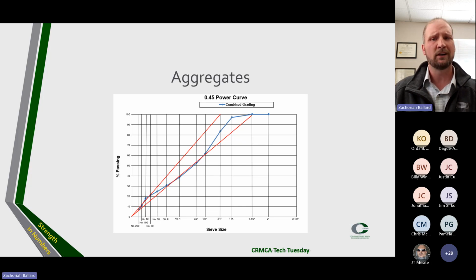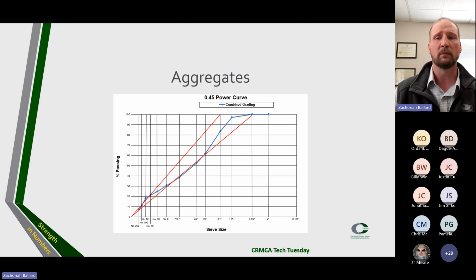We also have our 0.45 power curve. This started in the concrete industry in about 1907. It's now used kind of primarily by the asphalt industry. The 0.45 power curve uses a combined gradation to a best fit along a straight line, the cumulative percent passing chart. This is done by Fuller and Thompson in 1907. The straight line from the origin to the nominal maximum size has thought to be a maximum density of a combined gradation, which supposedly creates the maximum density and a minimum amount of voids in a mixture.